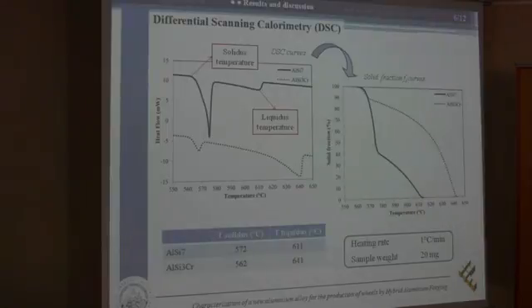Then, from the integration of the DSC curves, it was possible to calculate the solid fraction curve, so the solid fraction behavior against temperature. This was really important to understand the temperature range during which it was possible to apply the forging pressure, because it is applied between the liquidus temperature and 70% of solid fraction. So for this alloy we have a temperature range of 30 degrees, between 610 and 640 approximately.